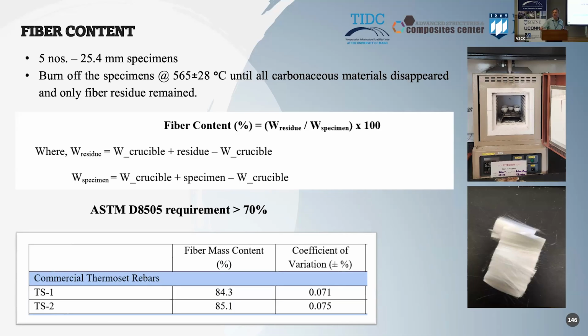These two commercial products have weight fractions in the order of 84 to 85%. And here is the requirement of the standard, more than 70%. So they meet that requirement. So this is an example of how bars can be qualified.